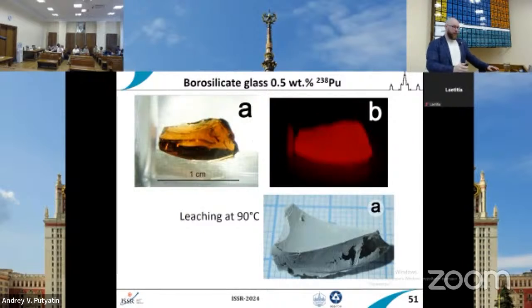Another example is borosilicate glass. So it's not a mineral-like material, but a pure glass material. Again, it was synthesized by Boris Burakov at the Radium Institute with, again, quite a high amount of plutonium-238. So plutonium-238 with a shorter half-life. That means that the dose can be accumulated much faster. And they described that the color is cognac-like, this nice brown color. And it was funny to observe the self-glowing of the materials in dark conditions.